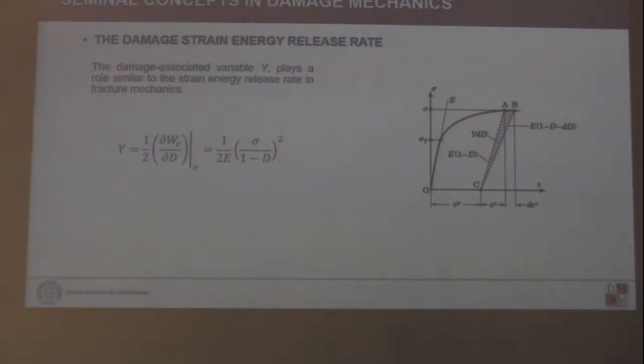releases the strain energy. So there is an equivalence also with fracture mechanics, because this is the same concept that Griffith formulated for a propagating crack, but here we don't have a crack. We have a smeared crack into the volume, and this quantity can be physically measured.